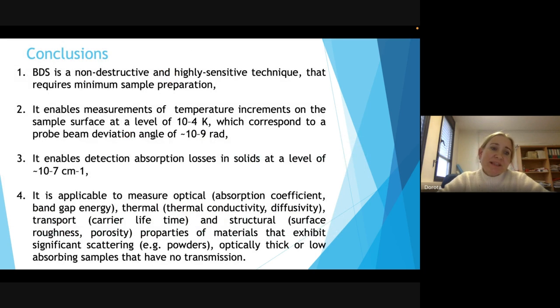So what can we say to conclude? We can say that the beam deflection technique has big potential: it is non-destructive and highly sensitive, and what is more, it does not require complicated sample preparation. It enables measurements of temperature changes of the sample surface at the level of a fraction of a kelvin, which corresponds to a beam deflection of 10 to the minus 9.